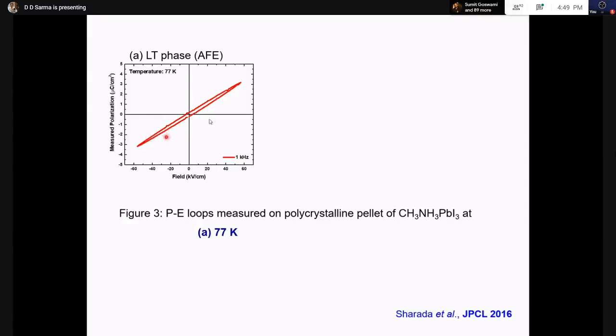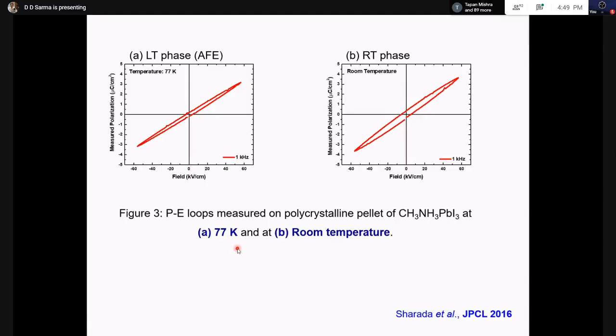The slight loop that is opening up comes from lossiness, which is a technical aspect. I'll not go into that. This is a measurement at 77 Kelvin. We are interested in the room temperature phase. What happens to the room temperature phase? Here is the data. You can again see it has nothing like a PE loop. It looks like a paraelectric, much like this, a little more lossy, so the loop is opening up a bit, but the polarization is essentially proportional to the electric field. That tells us the PE loop measurement clearly says it's not ferroelectric.